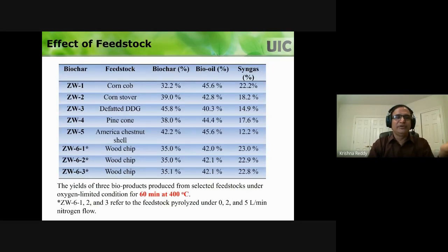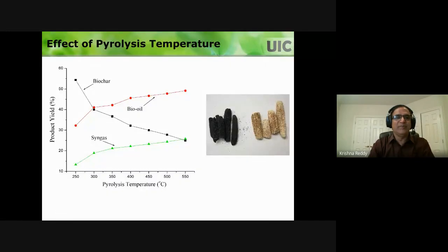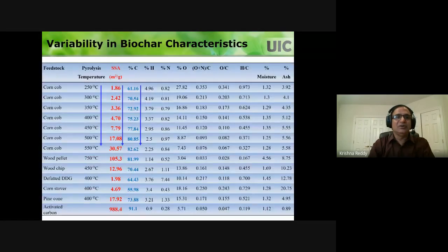Just as an example, I'm showing you here the effect of feedstock. You use different feedstocks with the same pyrolysis process, same temperature, same residence time, and you get different yields, right? So that's a problem. And if you increase or decrease the temperature, the amount of yield is going to be different. That's another issue. When you have these different temperatures and different residence times, the properties of the end product you get as biochar are going to be quite different. Just as an example, I'm showing you corn cob as the feedstock, and if it is made at different temperatures, you see the specific surface area is quite different, and the percentage carbon is going to be different. When these are different, the material is completely different, so it's going to behave completely differently. So you have to be really, really careful about how you make the biochar and what its properties are.